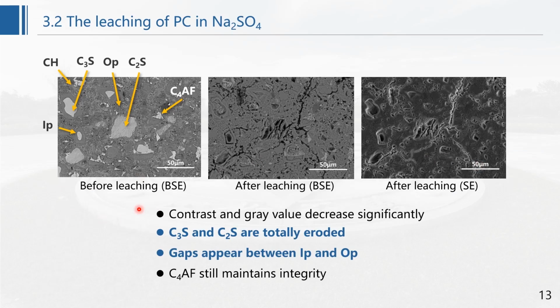Here are the BSE images of PC before and after leaching in sodium sulfate solution. Here is the image before leaching, here is the image after leaching. The contrast and gray value of the BSE image decreased significantly after leaching. The C3S and C2S are totally eroded and left holes in the matrix.